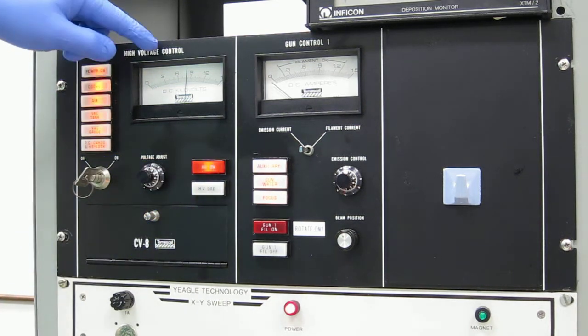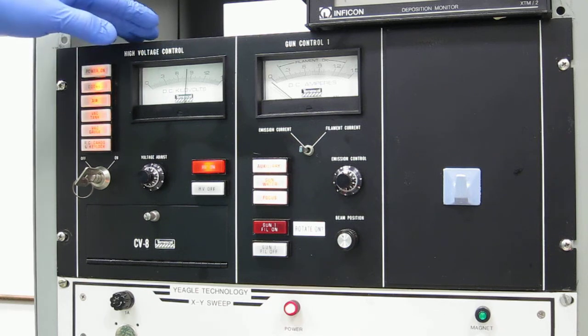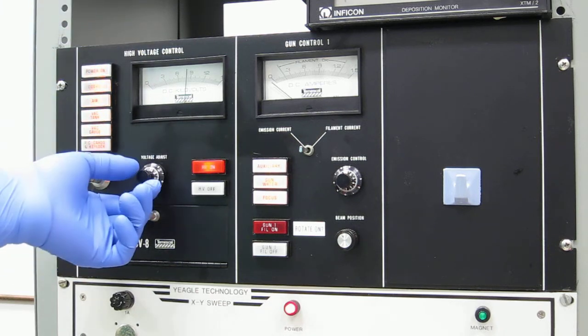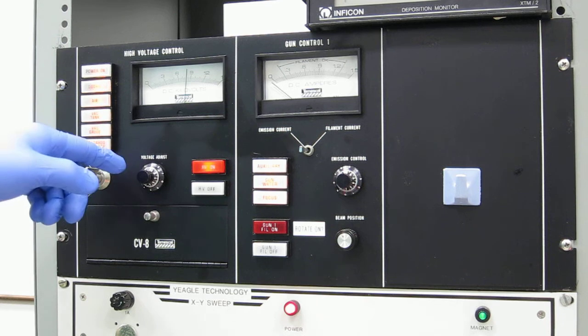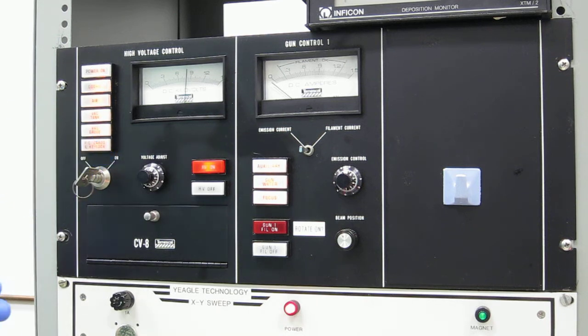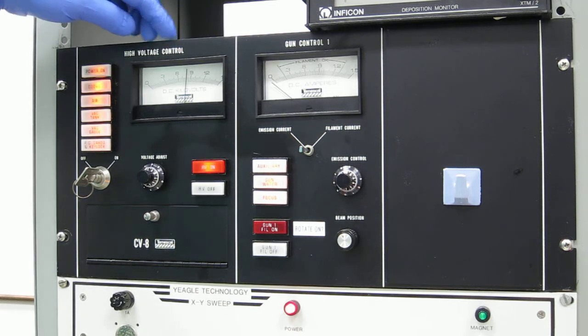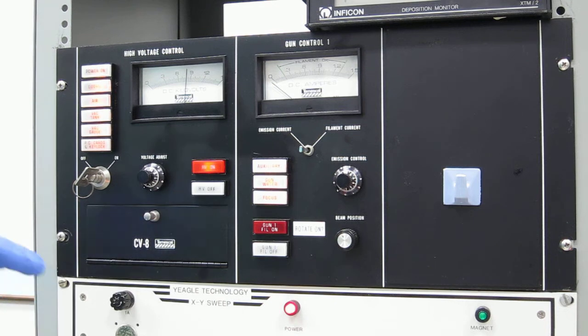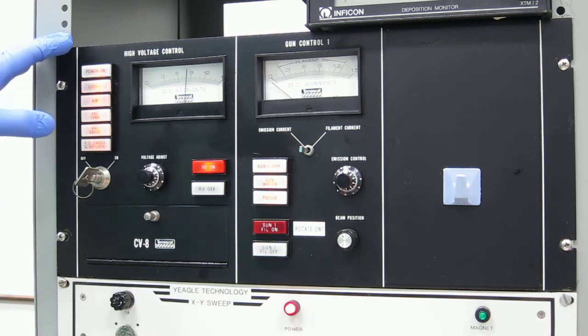Approximately 8,000 volts is now applied to the gun. This is adjustable. However, adjusting the high voltage adjusts the arc of the electrons. So too high a voltage or too low a voltage will result in the electrons not hitting the center of the crucible. It's important that you adjust the high voltage accordingly, and once it's adjusted to match the magnetic field, you leave it alone.